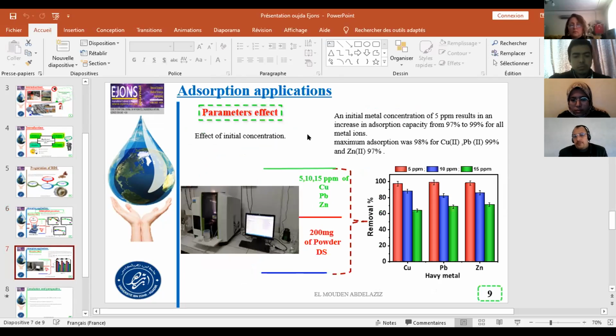Effect of initial concentration. The adsorption capacity of copper, lead, and zinc ions based on initial concentration is shown in the following figure. An initial metal concentration of 5 ppm results in an increase in adsorption capacity from 97 to 99 percent for all metal ions, as the figure shows. At higher concentration, maximum adsorption was 98 for copper, 99 for lead, and 97 for zinc, corresponding to the saturation of active sites on the adsorbent.